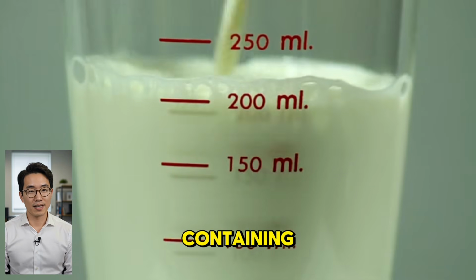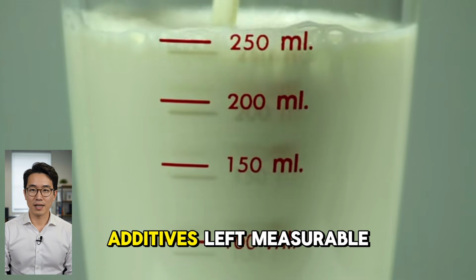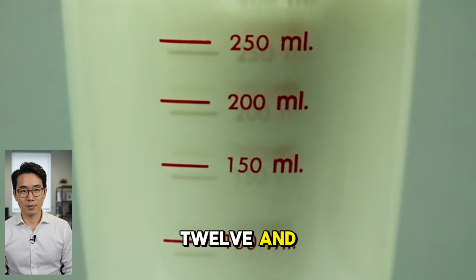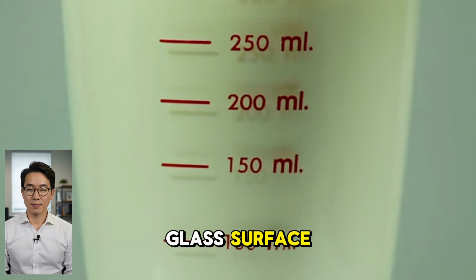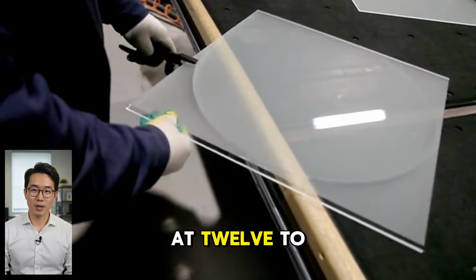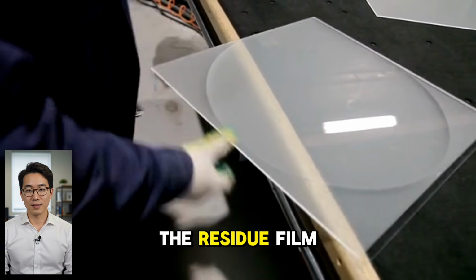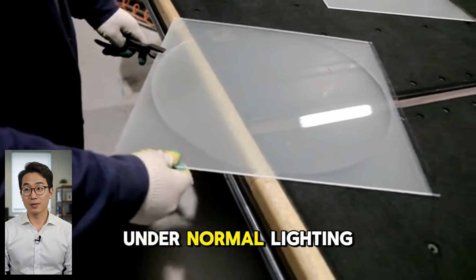Commercial glass cleaners containing synthetic surfactants and polymer additives left measurable residue films between 12 and 47 nanometers thick on the glass surface after complete drying. At 12 to 47 nanometers, the residue film is invisible to the naked eye under normal lighting.